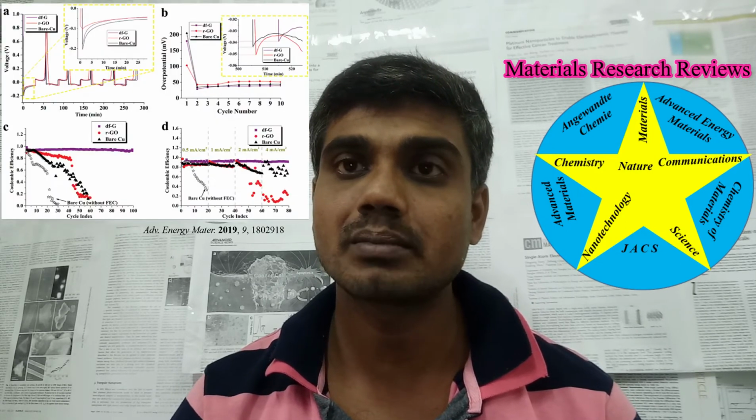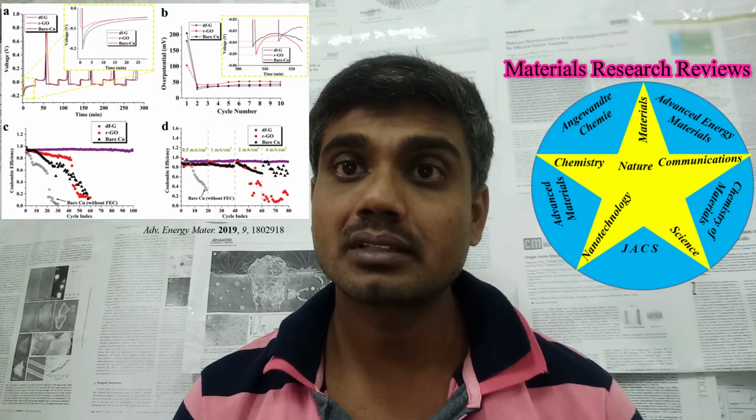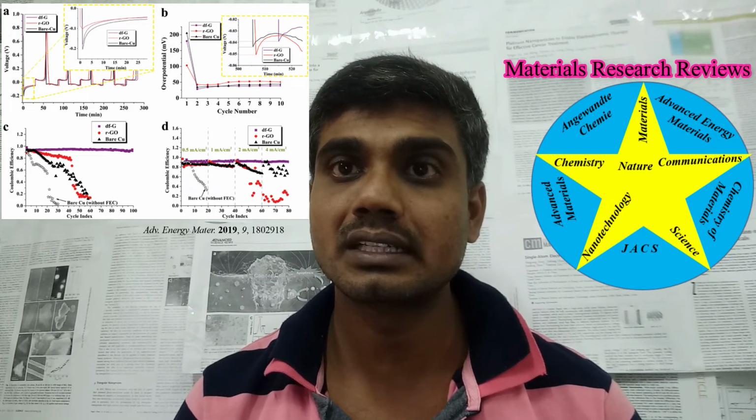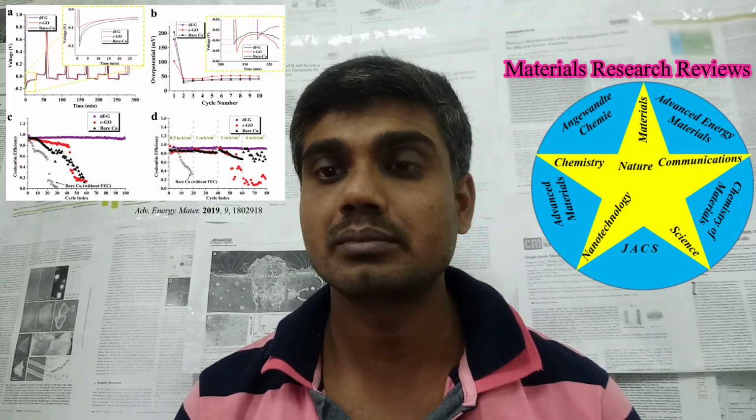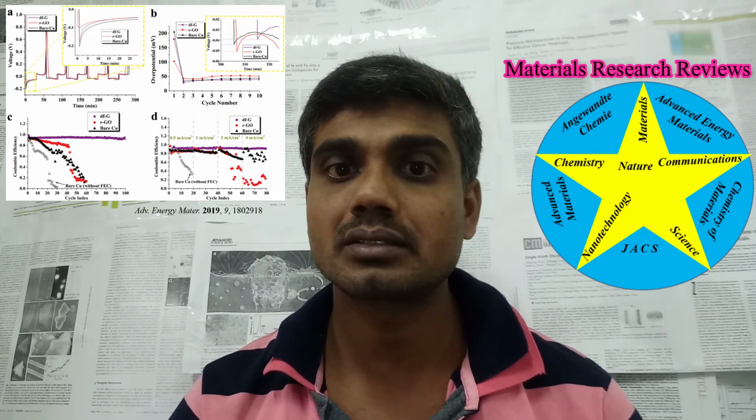Here also the graphene oxide only shows up to the 10th cycle plotted, because the graphene oxide is initially more active, and after that the impedance decreases. So after 20 cycles the graphene oxide and bare copper overpotential become unstable. So that is why only this plot is shown.